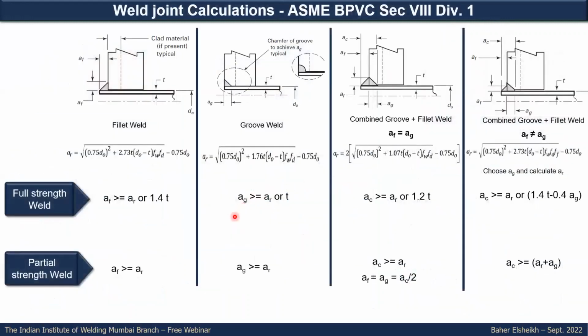Now we will have a look at how ASME Section 8 Division 1 calculates the required thickness or throat for the different weld joints of the tube to tube sheet. As we said earlier, there are two types of strength weld, full strength weld and partial strength weld, and also, if you can remember, the seal weld. But for seal weld, there is no calculation required. It is only a supplementary requirement for the sealant by the expansion, so no calculation required.